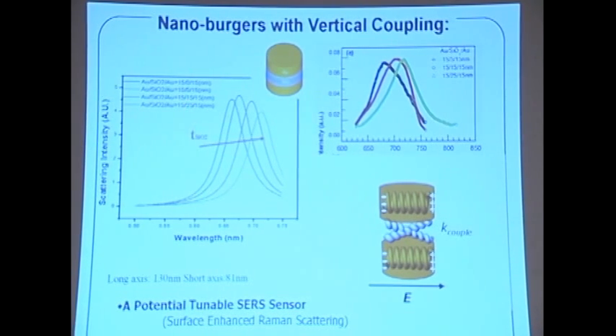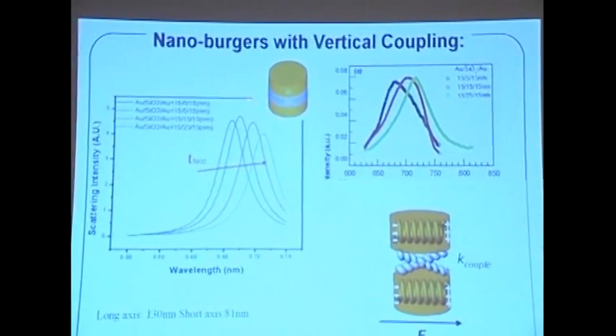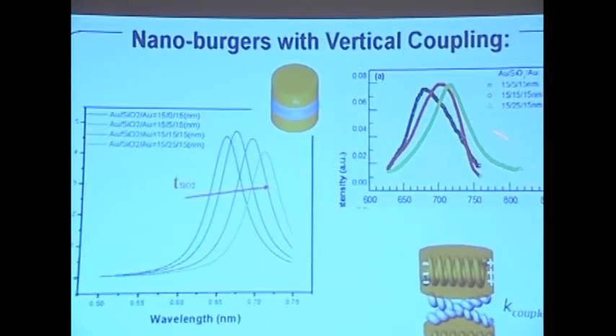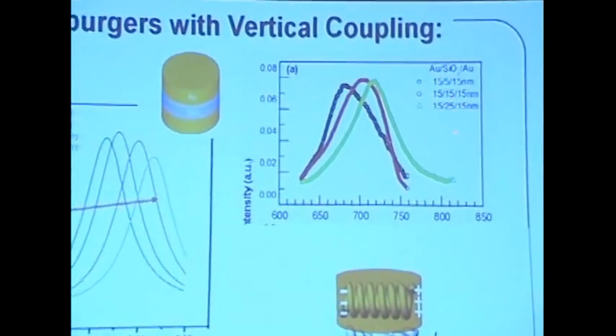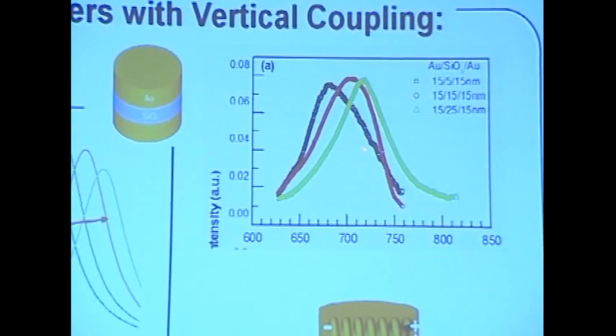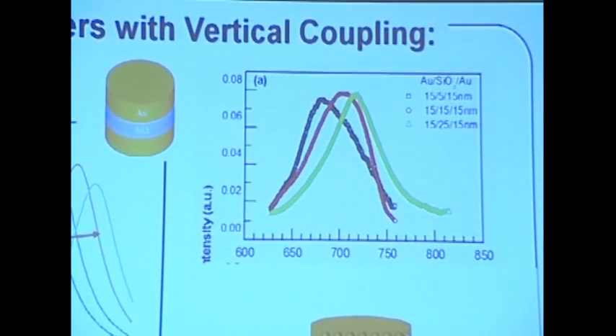We call it a nano burger. So basically, it's a metal-dielectric-metal structure. This is an experimental result. We spaced at 5, 15, 25 nanometers, and we observe a clear blue shift instead of a red shift.